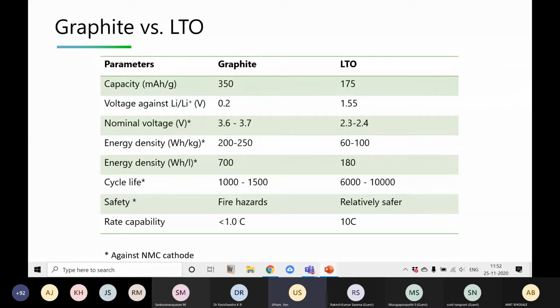So graphite having a theoretical capacity is around 350 milliampere hour per gram, and in case of LTO, it is almost again half of it. Voltage against lithium is 0.2 volt for graphite, and in case of LTO, it is 1.55 volt. Lower is better because final voltage of the cell is cathode minus anode. If your cathode voltage is 3.9 volt, then 3.9 minus 0.2 will come around 3.7. If it is 1.5, then 3.9 minus 1.5 will come around 2.4. So the nominal voltage of the final cell is going to be less. If you are going to use LFP, then again it is going to be even lower.